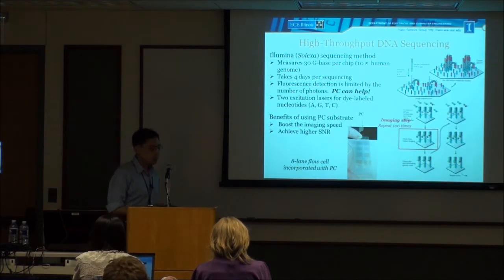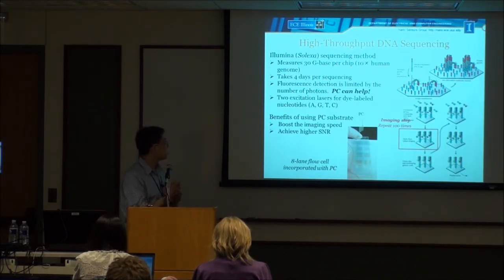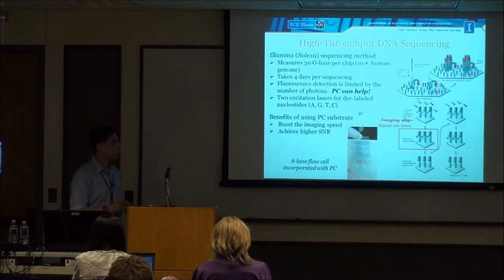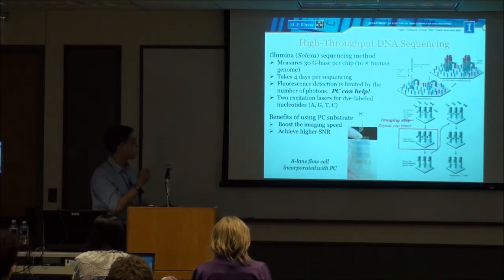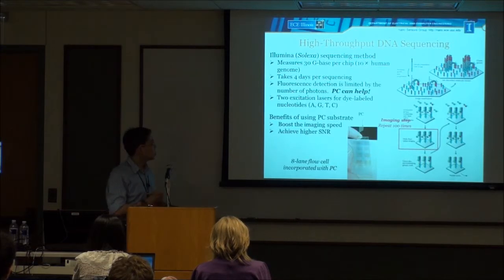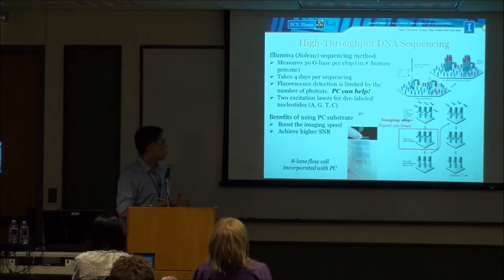The reason that we want to do two-color enhancement is because we were collaborating with a sequencing company, Illumina, trying to help them improve their sequencing throughput. Illumina is the leading company in the sequencing market. Their chip, which is shown here, is able to measure 30 gigabase pairs, which is about 10 times the size of the human genome. It takes them 4 days for each sequencing. In their measurement, the number of photons actually limits the speed of their scan. That's the step where our photonic crystal substrate can help.